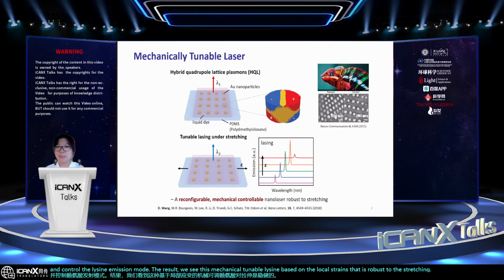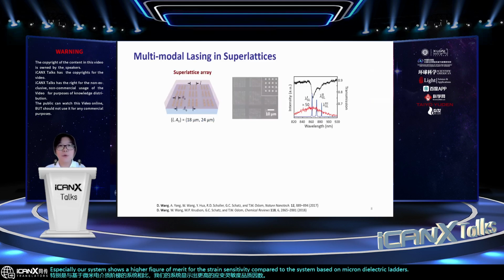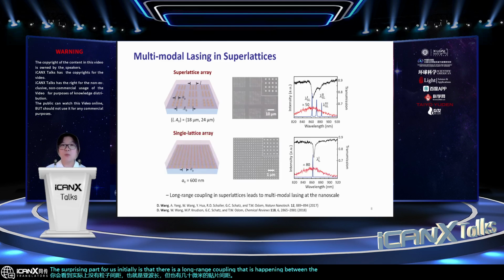Especially, our system shows a higher figure of merit for strain sensitivity compared to the system based on micron dielectric ladders. Another question we ask is how we can integrate multiple length scales into such a lattice. Here we call it the superlattice, where the particle spacing is sub-wavelength, but there's also a patch spacing that is tens of microns. The surprising part for us initially is that there is a long-range coupling happening between these patches, which introduces multiple resonances in the linear property.